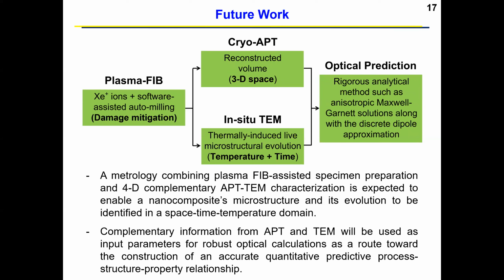First, the sample prep based upon the conventional gallium-ion FIB could potentially change the target specimen's microstructure, especially in the case of a radiation-sensitive sample like ours. Meanwhile, the xenon plasma FIB system utilizes inert xenon gas as the milling agent, and chemically inert xenon gas at an ultra low temperature has very low reactivity with the vast majority of elements, and is expected to minimize the undesirable secondary ion-matter interaction within target materials which are sensitive to other types of ion.